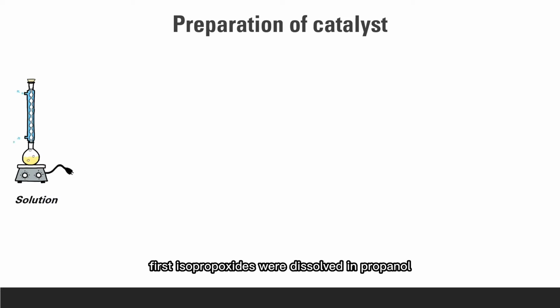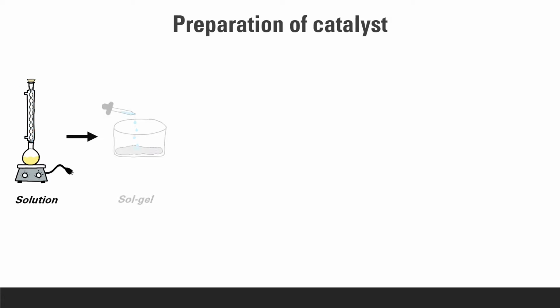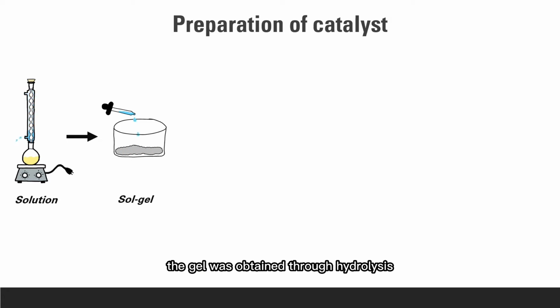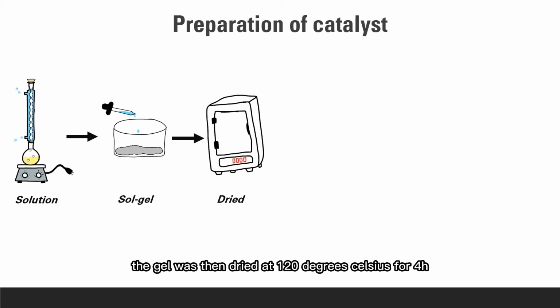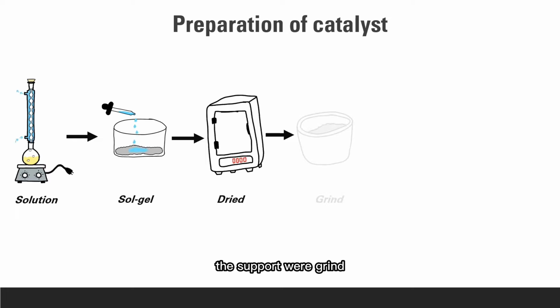In the preparation of catalysts, the supports were prepared by the sol-gel method. First, isopropoxides were dissolved in propanol. The gel was obtained through hydrolysis. The gel was then dried at 120 degrees Celsius for 4 hours and calcined at 400 degrees Celsius for 4 hours. The supports were ground.